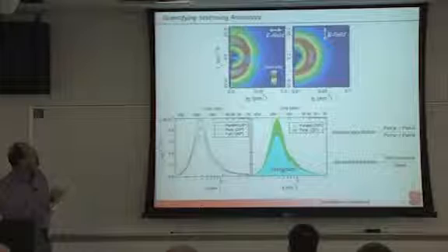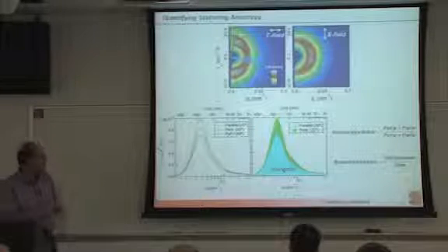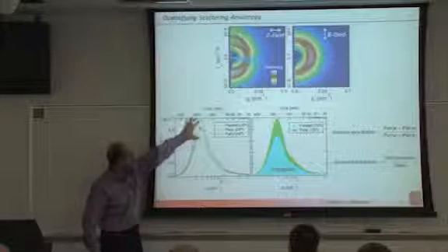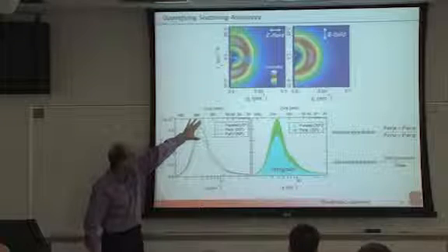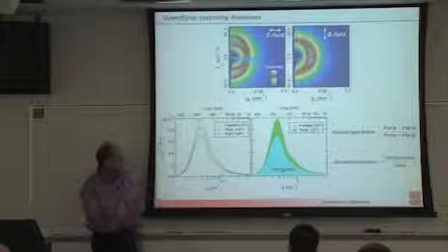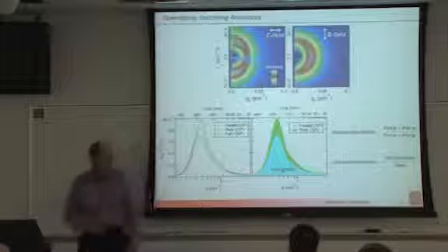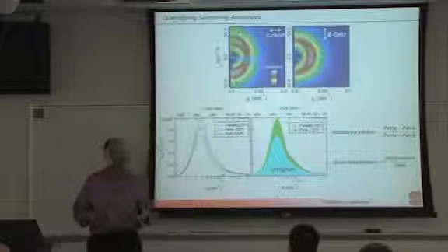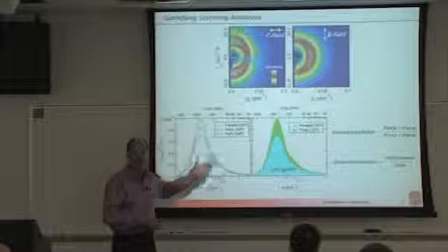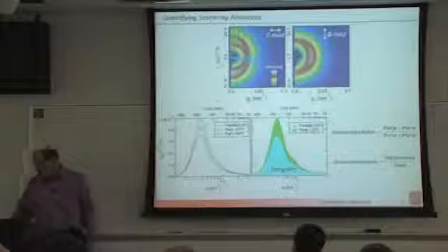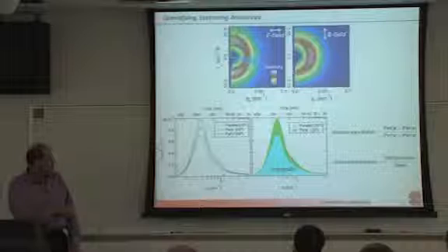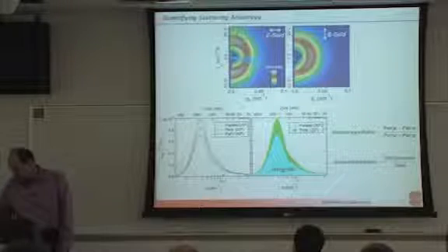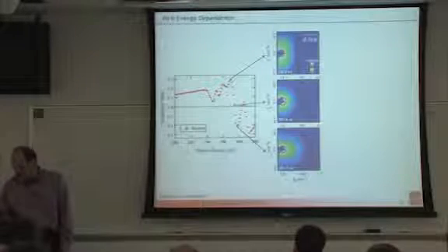So what we do is we just look at sector averages. Here, this is the full sector, and then this is a vertical and horizontal sector. We integrate the sector average total intensities, and we look at the difference over the sum. That's a phenomenological parameter that's easy to calculate from the data. So we look at this anisotropy ratio, essentially, of the scattering pattern and analyze that.